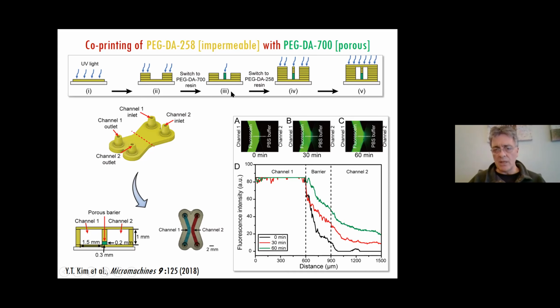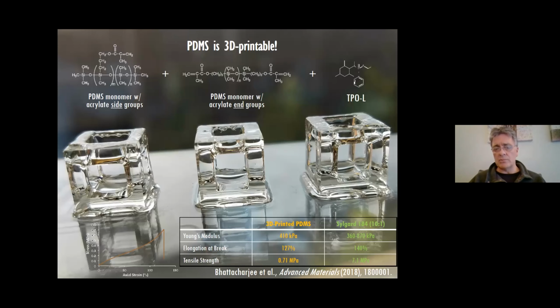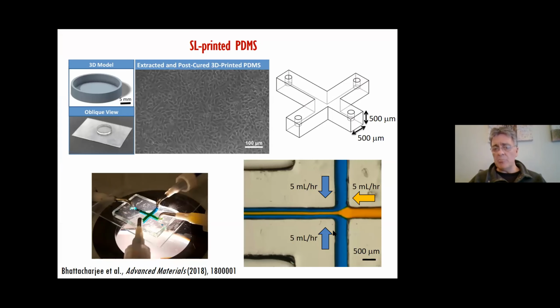It's all done by the machine. And we were also able to print PDMS because you can buy monomers of PDMS that are acrylated, and we mixed two types of monomers with the acrylate groups on different ends of the molecule, and then we found a good photoinitiator that was soluble in PDMS, and we were able to print PDMS in a way that was very transparent and with very good mechanical properties, very similar to Sylgard 184, and build PDMS channels as well with decent resolution.